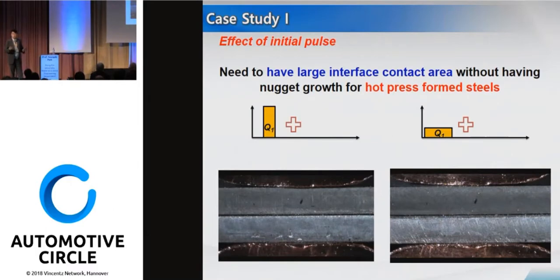What I notice, as you can see from the previous slide, is that in case of advanced high-strength steel, the nugget growth is very fast, which means that you need to have a very good large contact area before you grow the nugget. So what we need is a large interface contact area without having extensive nugget growth for the press hardened steels or any high-strength steel. So I tried two conditions: high current with short welding time, and low current with long welding time.